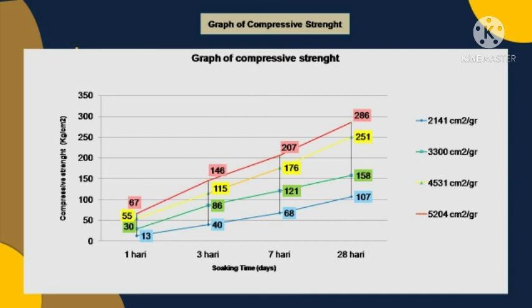As for the reason why fineness affects the compressive strength value, the smaller the cement particles, the less likely it is to form cavities, so that the cement mortar will be denser. The effect of the duration of setting time on compressive strength, as shown in the table, explains that the longer the setting time, the higher the value of the compressive strength.